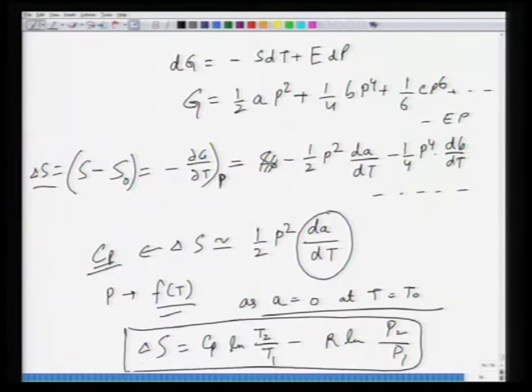So if there is a discontinuity in delta S at T equal to T naught, there has to be a discontinuity in the Cp. So second order transition is characterized by a discontinuity in the specific heat or entropy near T equal to Tc. So this is another feature, but without any evolution of latent heat.